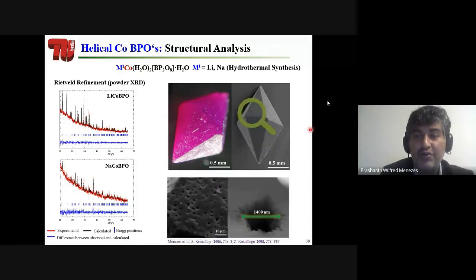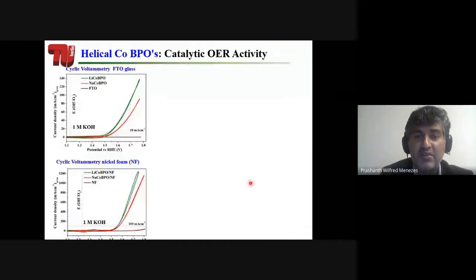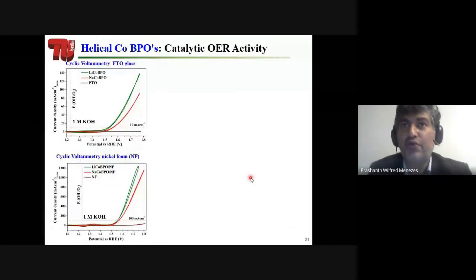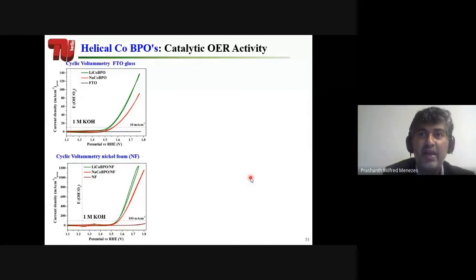Okay, so this hexagonal bipyramid also has holes. They are almost 1400 nanometers large. And as I already told you, we took this material and electrodeposited it on FTO or nickel foam substrate, and then did electrochemistry with it. We did all the reactions in potassium hydroxide electrolyte. As I told you, alkaline electrolysis is very, very important.